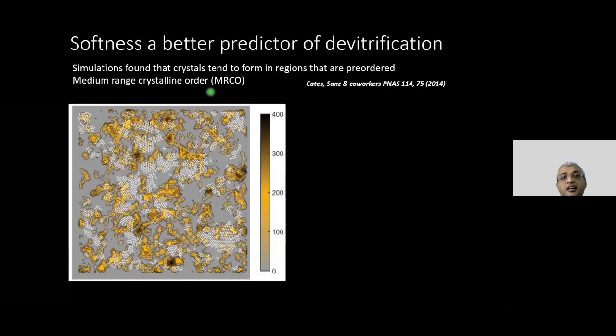Okay, and the studies that I mentioned to you earlier, which had alluded to the possible connection between structure and crystallization, I basically said that if you were to look at some sort of an order called medium range crystalline order, you would see that crystals later on tend to grow in those regions in the glass. And we also did that analysis.